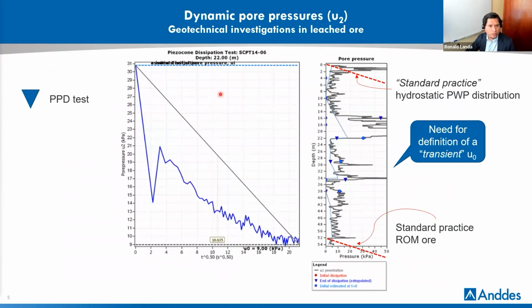This is an output of the dynamic pore pressures. This is just one test, a pore pressure dissipation test by the CPT. It's used for a definition of the transient pore pressure at the equilibrium. I say transient because it's actually not at equilibrium, because in a heap leaching, it's very dynamic and it changes all the time. So it's important because the pressure heads are practically transient all the way until irrigation is ceased. But they can be controlled under thresholds as we calculated, since we're not going to avoid saturation. That's some of the topics that they were talking about yesterday. So saturation of fines dominated layers within a heap is what we need to control. Sometimes we use vibrating wire piezometers along the profile, so we can estimate more reliably this u0 profile.